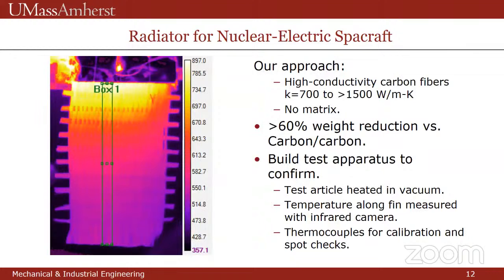So our approach was to incorporate these high thermal conductivity fibers. And one of the competing technologies for this temperature range is carbon-carbon composite radiators. These have a couple of problems. They're a lot heavier than our design because the carbon matrix contributes very little to the conduction of heat, contributes a lot to mass. It also contributes a lot to structural strength, but in a place you want not to have it. The carbon-carbon radiators fail by delamination of the braze joint between the carbon-carbon and a metal heat pipe. And by going to 10 micron fibers, we prevent that delamination.